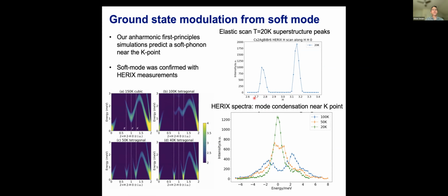But if we look at the spectrum here from HERIX close to this K point, we find that this distortion occurs at around 40 Kelvin. So if you're at 100 Kelvin, you see well-defined phonons at finite frequency here. At 50 Kelvin, you're getting very close. This is nearly condensed here in the orange trace. And then below the transition, you get a superlattice peak effectively at this modulation wave vector.